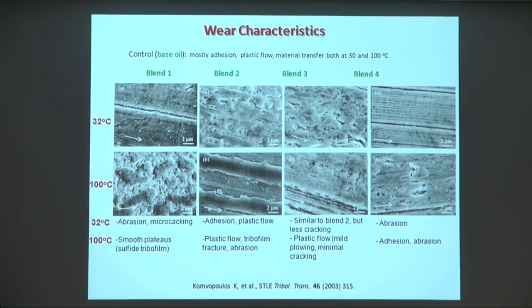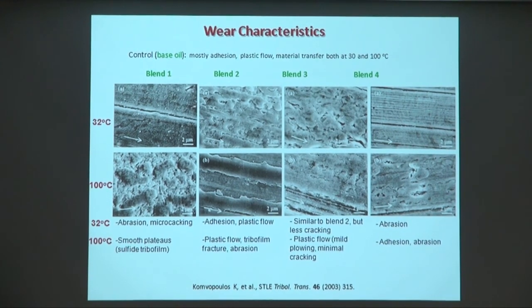Often in industry, they tend to say whether we have mild, medium, or severe wear, and that is not really revealing how to solve the problem. You need to know the mechanism. What kind of wear mechanisms? There are various types by which material is removed, various wear mechanisms, such as abrasion, adhesion, delamination, plastic flow, and you can see the morphologies that we have here when these films are forming or not forming, what is happening.